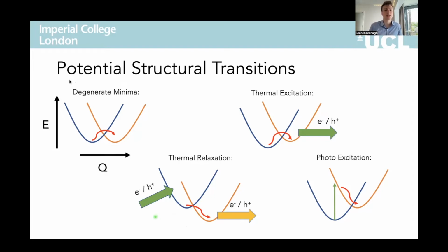and in our work on the cadmium vacancy. However, another possibility is that you could start from the ground state arrangement, and then if you have a low-lying metastable state with a relatively low kinetic barrier, you would end up with a certain thermal population within this metastable state. If this then has a fast capture route, this could potentially catalyze our recombination cycle as well.